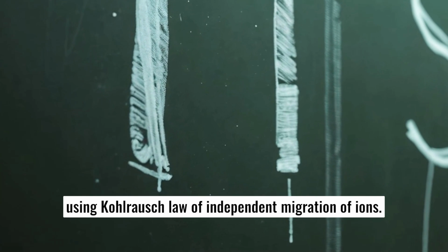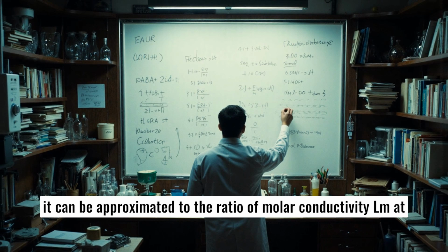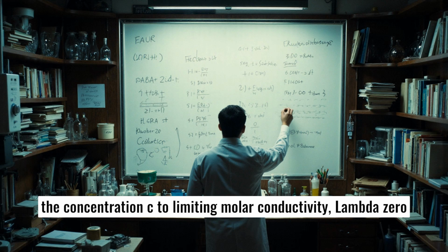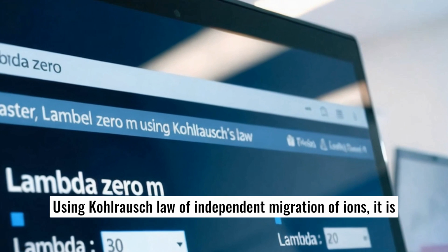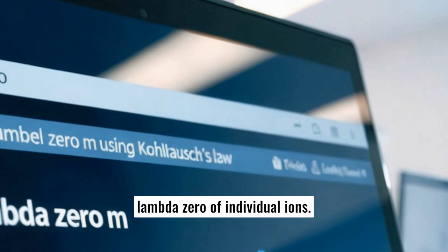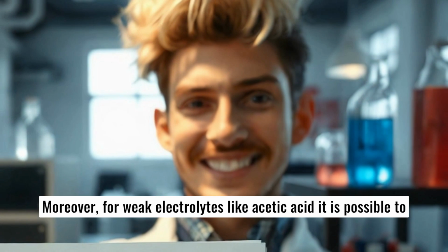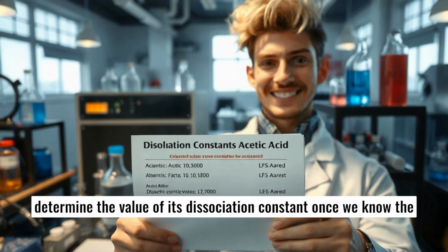Therefore, Λ0m for weak electrolytes is obtained by using Kohlrausch law of independent migration of ions. At any concentration C, if alpha is the degree of dissociation, then it can be approximated to the ratio of molar conductivity Λm at the concentration C to limiting molar conductivity Λ0m. Using Kohlrausch law of independent migration of ions, it is possible to calculate Λ0m for any electrolyte from the λ0 of individual ions. Moreover, for weak electrolytes like acetic acid, it is possible to determine the value of its dissociation constant once we know the Λ0m and Λm at a given concentration C.